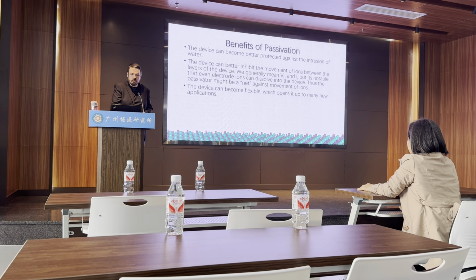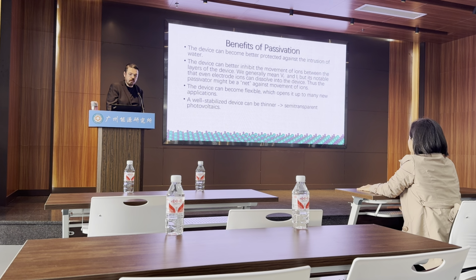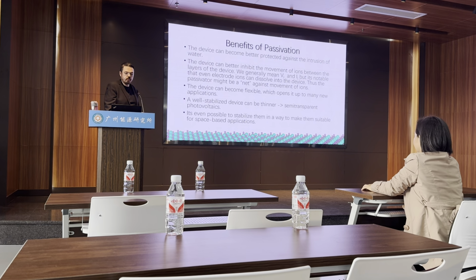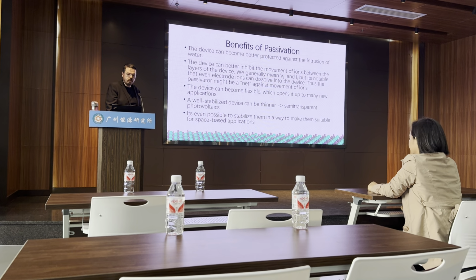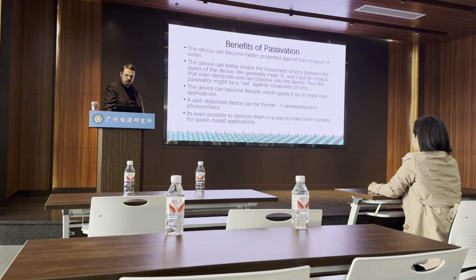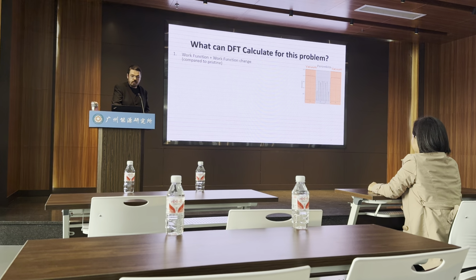So the device can become flexible, which is really cool. It opens up very many new applications which are not available to silicon-based cells. And with a well-stabilized device, we can make it thinner, thus semi-transparent, thus we can put it on buildings. Buildings are a big source of global warming and CO2 output, so actually pretty important. And the final thing is, space is the final frontier. It's even possible to make them stable in space. And actually in space, they're sometimes even more stable than in terrestrial conditions. And this has to do with radiation hardness. It turns out they're more hard than silicon, which is impressive. So what can DFT do for us?